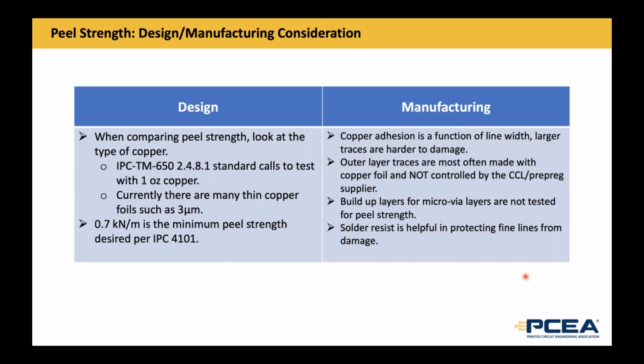And Tony, do you want to add some things to consider for manufacturing? Sure. So the thing about copper adhesion, and this is the part that I think a lot of people don't really understand, that peel strength value of 0.7 kilonewtons per meter is prorated, which basically means if the line width goes down, it's a function of the total adhesion of that circuit. That means the thinner circuits are not adhered to the surface as well and are more prone to damage. The finer the lines are, the easier it is to damage them.